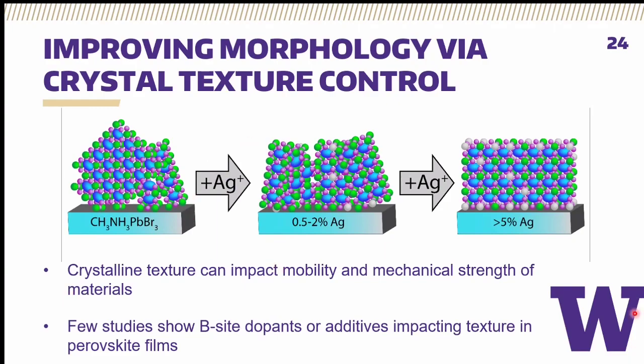Crystal texture is important for a variety of different mechanical and electrical properties, and for improving them in optoelectronic devices. And in perovskites, this control over crystal texture is normally done by adding these long organic carbocations, these 2D spacers, so to speak, which, while doing a great job of controlling morphology and actually improving stability of the perovskites, are significant hindrances to electrical transport through these films. Few studies have shown that you can get a similar sort of crystal texture with a B-site additive.